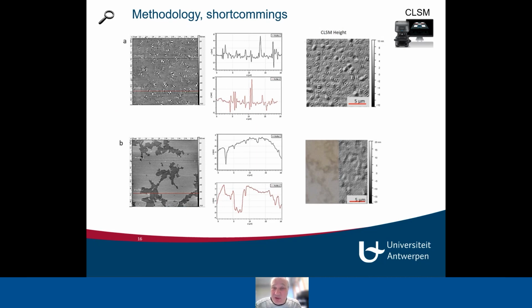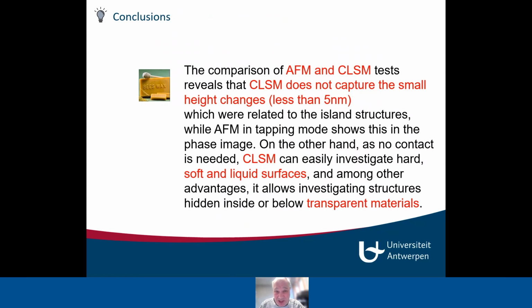Then we had some shortcomings, of course, with the confocal laser microscope. One of the shortcomings is that, of course, an AFM is more sensitive, and that played a role in the measuring of these secondary phases. But if we combine optical and laser, we still could see the effect. The lowest scale or the resolution of the laser is around 5 nanometer, and if you look at the profiles or the height differences, you can see that of course phenomena lower than 5 nanometer we cannot observe. So to finalize, we can see that these methods give more or less the same results. We can use them both.